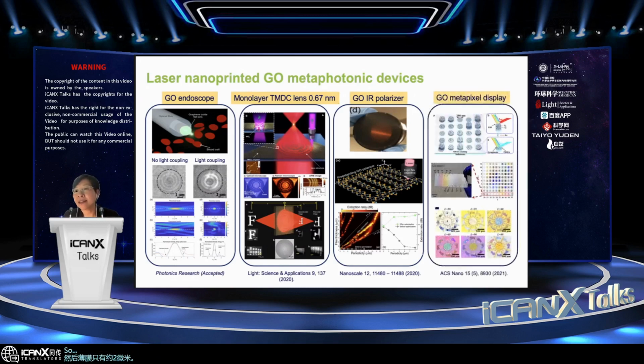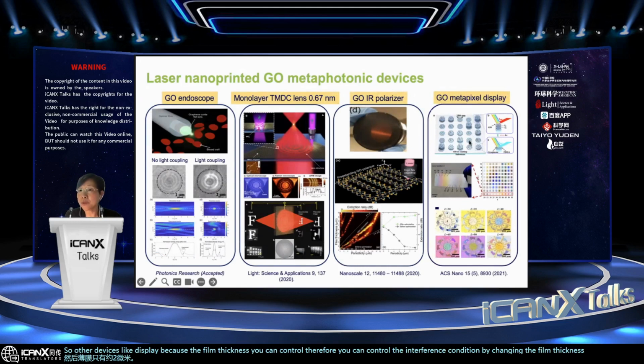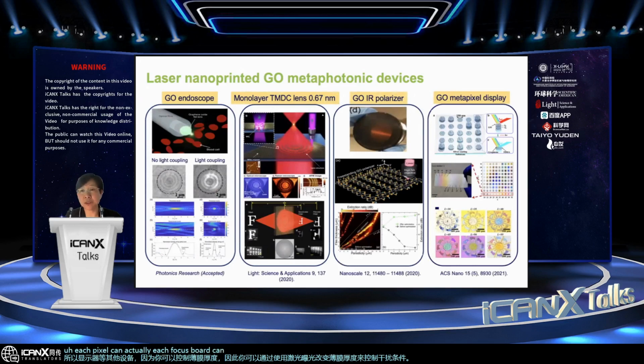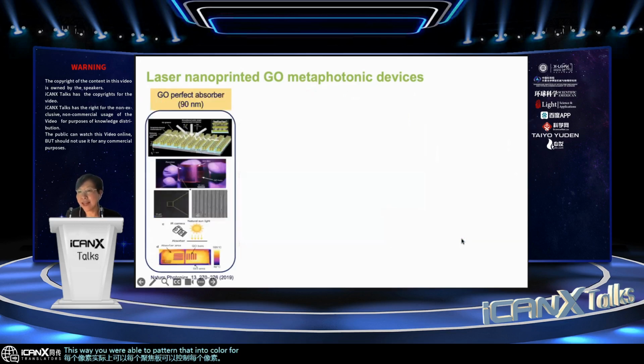So other device like display, because the film thickness you can control, therefore you can control the interference condition by changing the film thickness using laser exposure. Each pixel can actually, each focal spot can control each pixel. This way you are able to pattern that into colorful displays. And then display can actually change color when you illuminate with different light. On the other hand, so this laser nanoprinting can also introduce what we call that energy device.